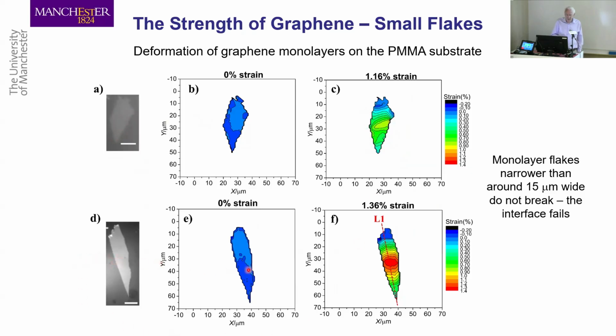This one here is a fairly narrow one. Again, we couldn't break it. It just got a high strain in the middle. We just couldn't break it. So there seemed to be a size effect here. The big flake, we broke it easily. The smaller flakes, we couldn't break.